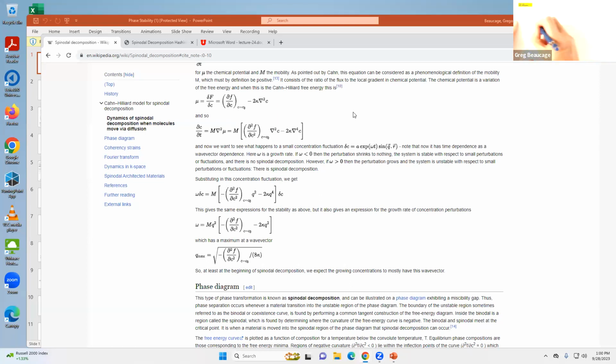If you do light scattering, shoot a beam of light that's about microns in size, like 0.6 something for a red laser, through a sample, and the phase separation is happening on a micron scale, then what you'll see if you put a piece of paper here is the main beam, and then there'll be a cloud here, right? And that's Q max, the distance from there to there.